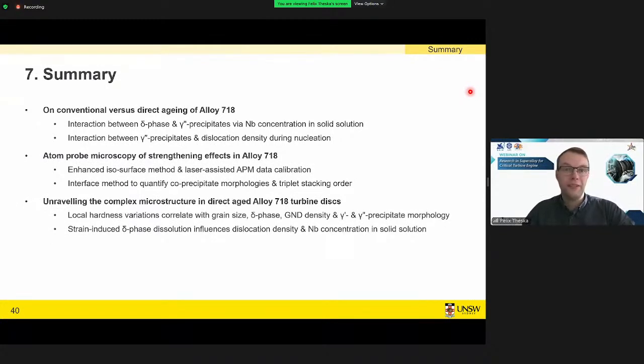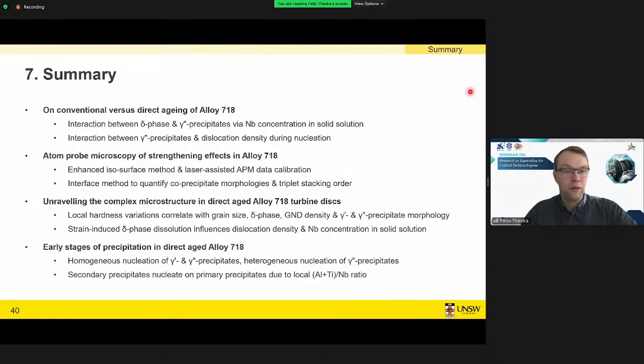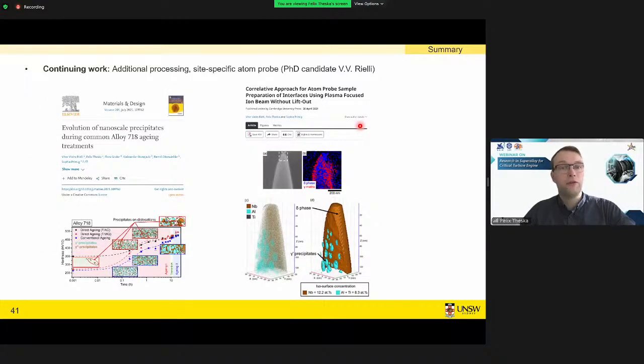These are incredibly complex because we have a lot of factors during the manufacturing in the microstructure playing together. But we can also quantify our early stages of precipitation, where we have observed homogeneous and heterogeneous nucleation. And we found that the secondary nucleation is favored by the change of the local chemistry. So that's been my work in our group.